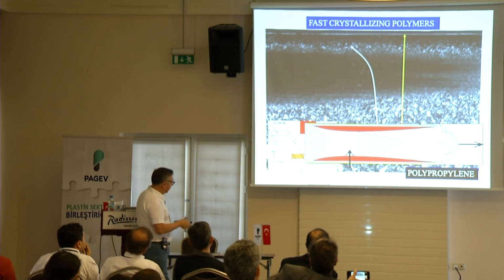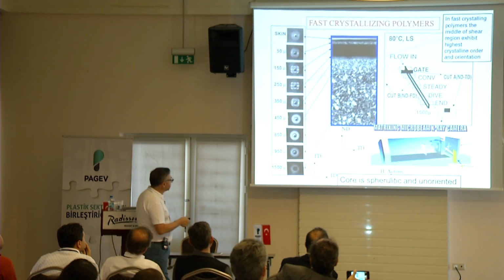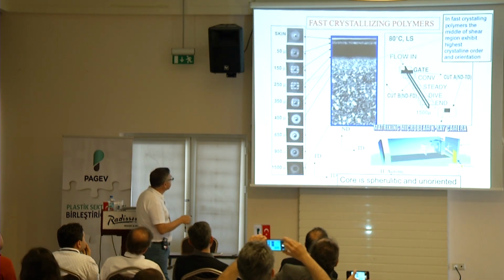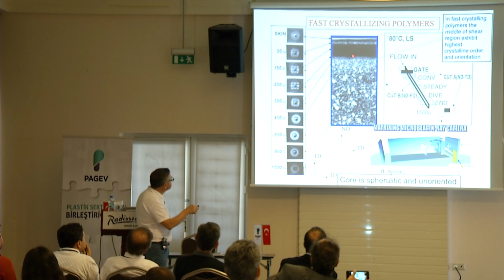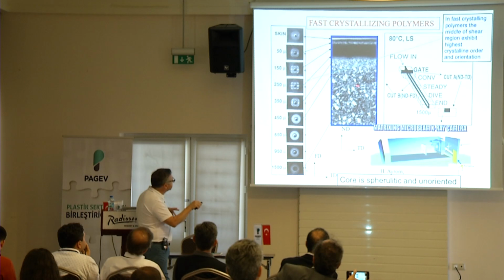Well, if you don't believe me, we actually did an X-ray diffraction. We still haven't published this yet, believe it or not. So you have an X-ray from skin all the way to the core. You see that in the dark regions, you don't need to know what the X-rays are. Just know that there's a difference in sharpness. The sharpness indicates polymer chains are oriented this way. When the sharpness disappears, that means it's less oriented. That's typical of a spherulitic structure. If you watch it carefully, what you see is that these are small crystals.